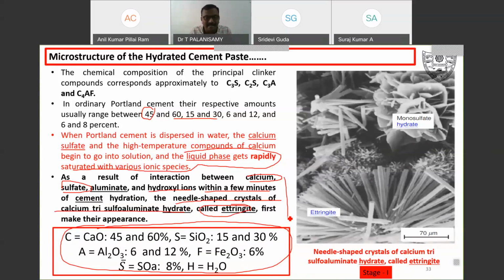As per theory, we can say how the ettringite structure forms. Calcium sulfate, aluminate, and hydroxyl ions, within a few minutes during the cement hydration process, form needle-shaped crystals. That is called ettringite, calcium trisulfoaluminate hydrate. How does it show? Using the scanning electron microscope, you look at cement-based structures like this. So this is represented as the ettringite structure. The needle-shaped crystals of calcium trisulfoaluminate hydrate are called ettringite.